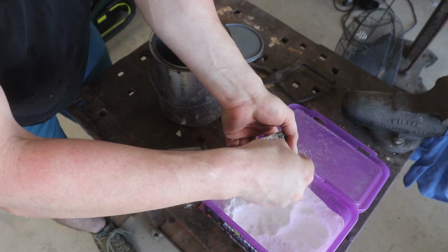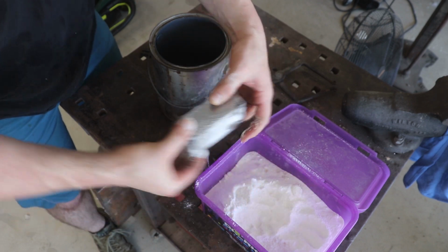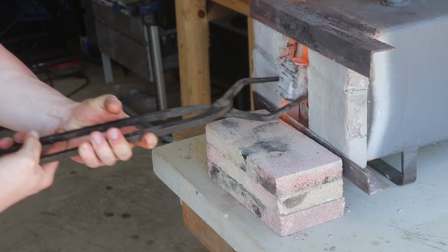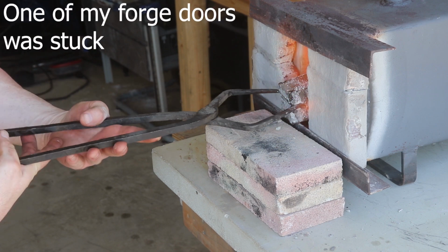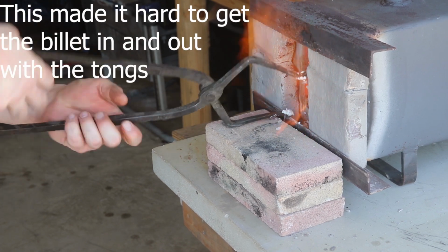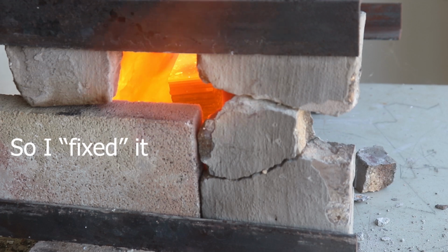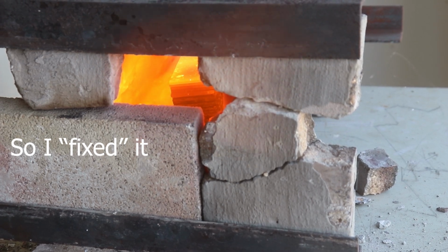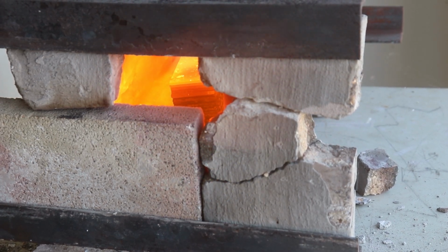Alright, now I got some flux on these. I'm going to take them over to the heat and pop them in. See that billet is starting to get red hot all around the edges. I'm going to go ahead and pull it out and squish it as flat as I can get it in the press. Then we'll reflux it, toss it back in the forge and get it up to welding heat.